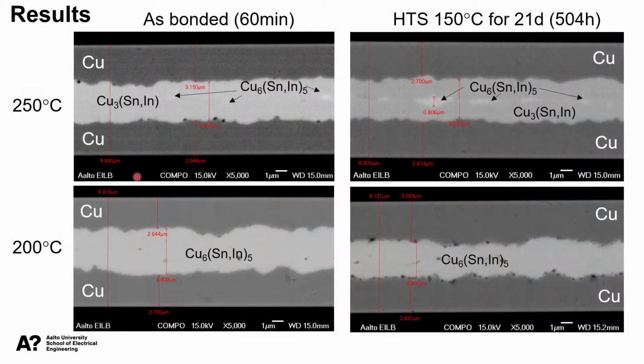This slide concludes our findings on the interconnection microstructures. In the left hand side, we see the as-bonded microstructures, and we can conclude that at 250 degrees bonding temperature, the interconnections were mainly composed of copper-3 tin phase, and on the other hand, when bonding temperature was 200 degrees centigrade, then the microstructure was completely copper-6 tin 5 phase.